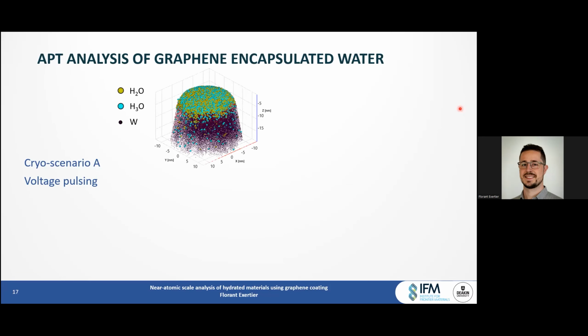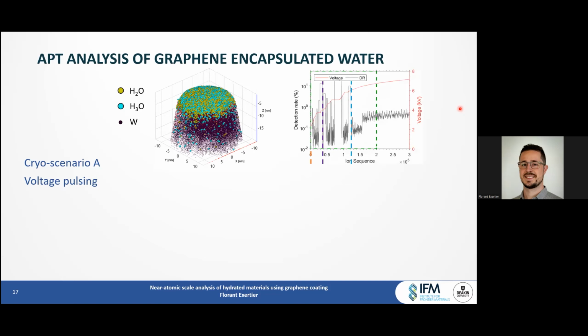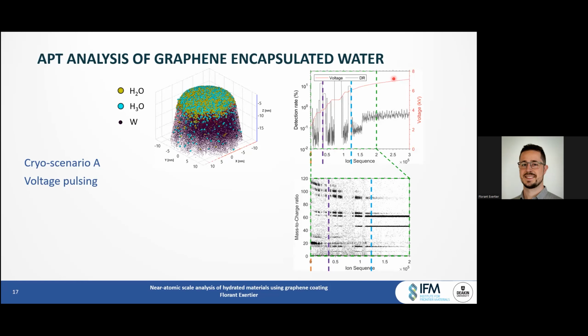In the 3D reconstruction, we can see the successful detection of water-related ions, such as H2O and H3O at the tip. And here are the voltage evolution and the detection rate, as well as the mass history, showing the evaporation sequence. The evaporation of water always started at a relatively low voltage, sometimes plateaued for a bit, and then increased once the water was removed.